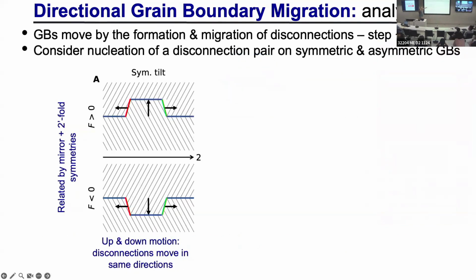So as I mentioned before, the way a grain boundary migrates is you form this pair of disconnections. So these are steps here. And if I make the boundary go up, these two steps form like this, and they migrate outward. If it's going to migrate down, the double kink, or the double pair of disconnections, goes the opposite direction. And then again, these things go outward.